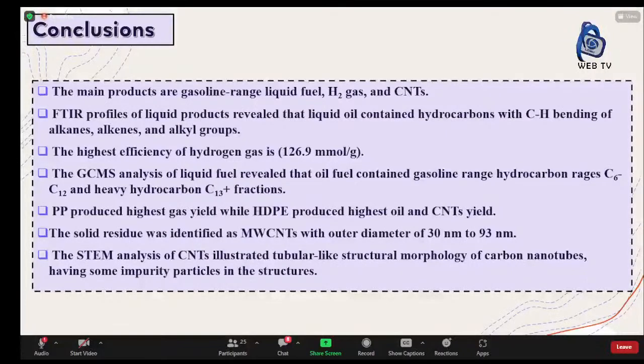The PP produced the highest gas yield, while HDPE produced the highest oil and CNT yield, but the mixture of these two produced small hydrogen and liquid yields, but the solid product was more structured compared to the first two cases. The solid residue was identified as multi-walled carbon nanotubes with an outer diameter of 30 nanometers to 93 nanometers.